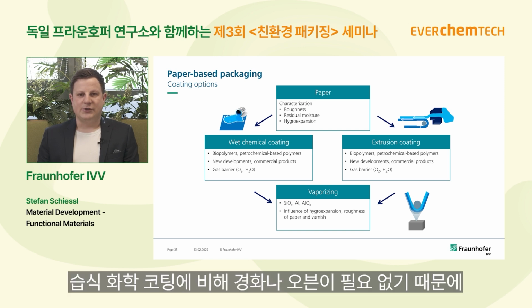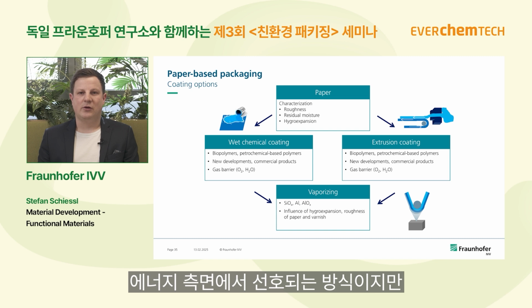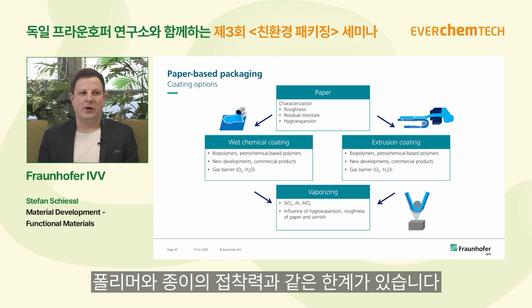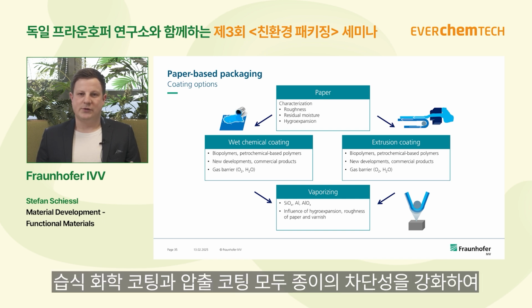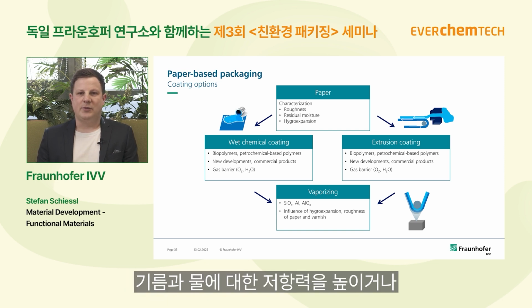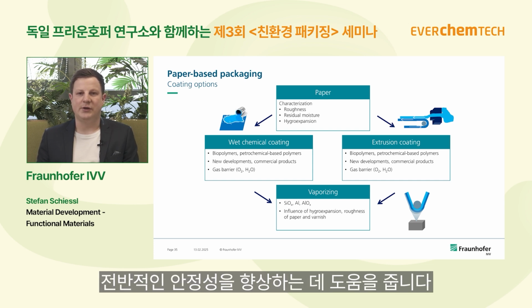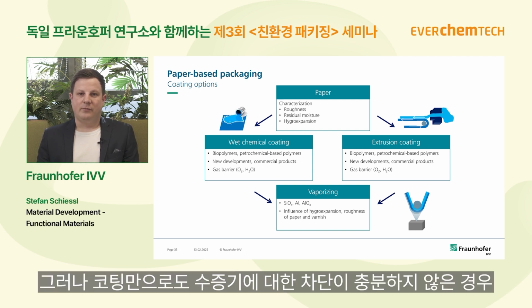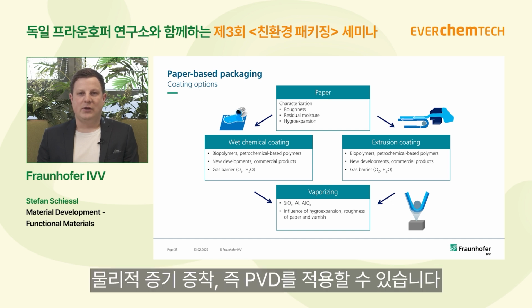This is from an energetical point of view favored, because you need no curing, no oven in comparison to the wet chemical coating, but there are also limitations, for example the adhesion of the polymer to the paper. And both of the systems, so the wet chemical coating and the extrusion coating, they help us to modify the paper in a way that we increase the barrier, for example, or increase the stability against grease or water. But if the barrier against water vapor is still not good enough by the coating, then we have the option to do a PVD, physical vapor deposition.